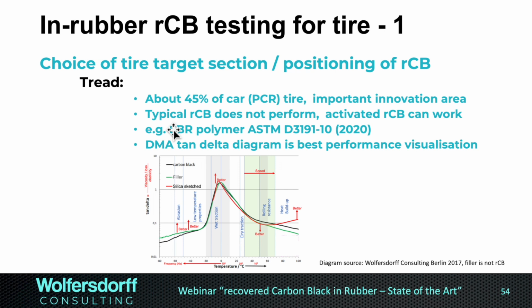Typically, recovered carbon black does not perform in the tread. I have seen some activated recovered carbon blacks that can work in the tread, but they're still not as good as a 300 type or furnace carbon black. The polymer to test in would be an SBR polymer, and we could use the standard for carbon black testing in SBR 3191. What we would do is a DMA, a dynamic mechanical analysis, with a tan delta diagram. The tan delta is the ratio of the loss modulus over the elastic modulus, and then we can plot it over the temperature.